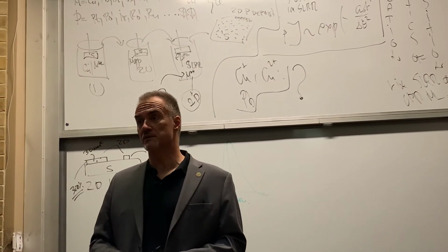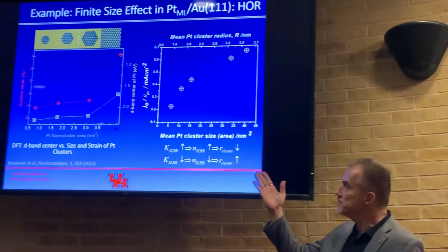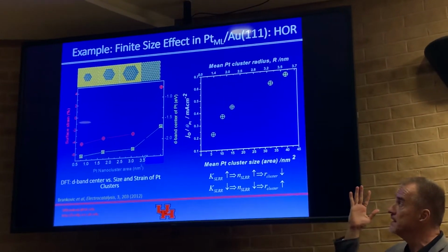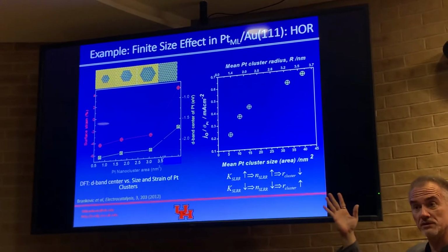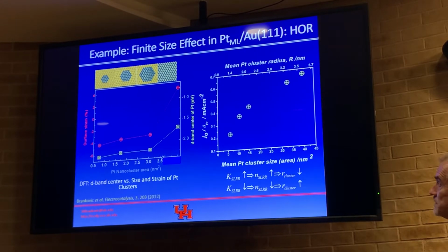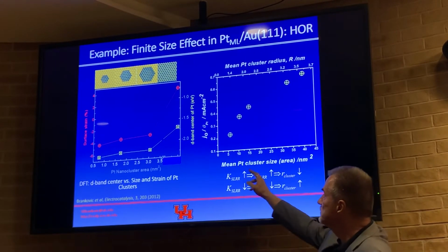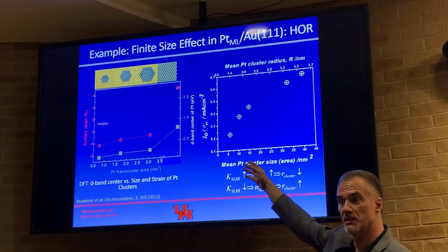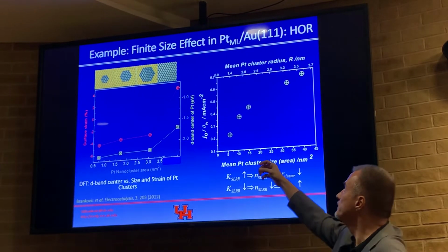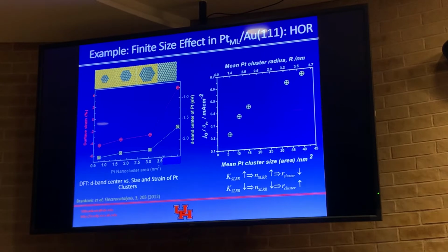So it's representative, kind of, not really average, but a representative value of the whole clusters on the surface. And so when we represent what we measure for the particular catalysts that are purposely synthesized using different conditions, with the approach we described, we see significant difference in the activity. For example, for the population dominated by relatively small clusters, the exchange current density normalized per cover is 0.2. Yet, for the ones that are about 40 square nanometers, it's about 0.6. So it's a ratio of 3 times, 300%.